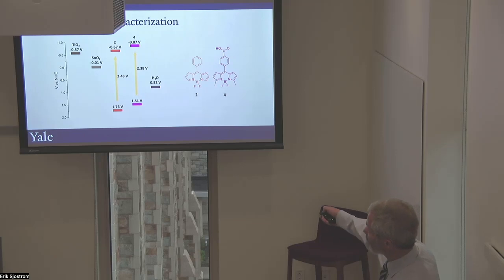In this case, for example, we've got a reduction potential or excited state potential that is pretty nicely matched to inject electrons into TiO2. It's pretty close, but slightly more negative. This is probably too oxidizing, really. The consequence of that is that the energy here is too high, which means it doesn't absorb as much of the visible spectrum as we'd like. So if we could optimize this, we might want to move this potential up to maybe around 1.2 volts and leave this one the same. That's easier said than done, but if you could do that, you should absorb much more of the visible spectrum and still have it functioning. So that's a design for the future. Right now, this is where we are.